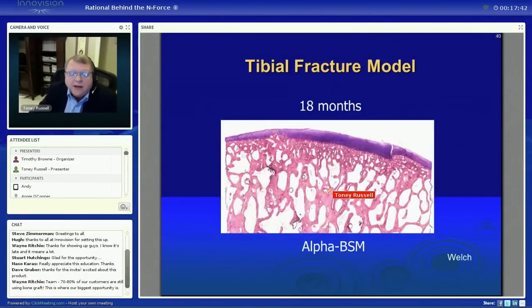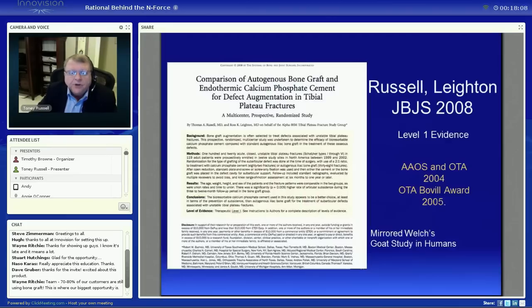This is what it looks like at 18 months. This is the alpha BSM, which is the precursor of the beta BSM and the CarriGen. And what you see is the cement is gone. And what's happened, now we have these nice healthy trabecula again. So this material helps regenerate normal trabecula. And as it gradually has this cell-mediated resorption, the articular surface reduction is maintained. So this actually can heal the way it's supposed to.